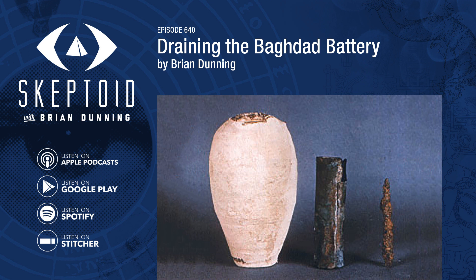Koenig's conjecture was that the battery may have been used for electroplating jewelry or bits of art, which is actually not a terrible hypothesis. Gilding was indeed well known in the world during the Parthian period. However, we do know how they did it, and it wasn't Koenig's way. The technique in use was called mercury gilding, or fire gilding. Gold or silver dissolved in mercury is applied to the object to be gilded, then heated to volatilize away the mercury, leaving the coating of precious metal on the object. Today it's trivial to verify that this is the method used on a given object, as the gilding still contains significant mercury and other chemical signatures. All gilded objects from the period use this method. None has been found to have been electroplated.